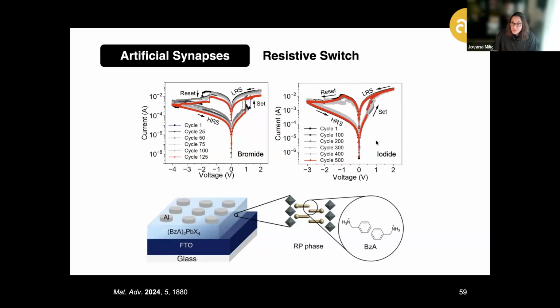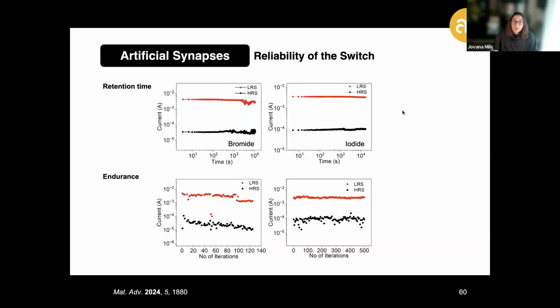Importantly, this switch between the low and high resistance state through the corresponding either gradual or abrupt set and more gradual reset process in these systems can take place over a number of different cycles, several hundreds of cycles in particular, where the reliability of these cycles is further analyzed by looking into their retention as well as endurance over a number of these iterations.